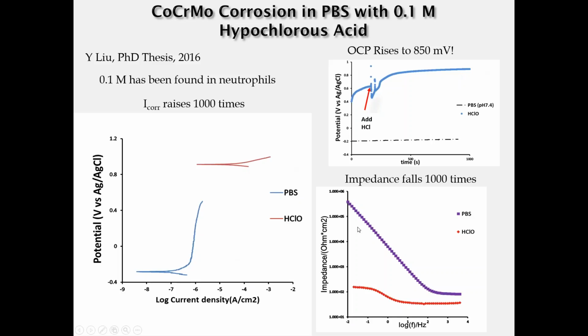phosphate buffer. The resistance of the oxide films of cobalt chromium in the presence of this 100 millimolar hypochlorous acid is down about 3 to 4 orders of magnitude. So a dramatic decrease in the resistance of the oxide. Clearly, the presence of this species in the solution is damaging the oxide film, raising the oxidation potential, and moving the alloy up into a very severely corroding condition.